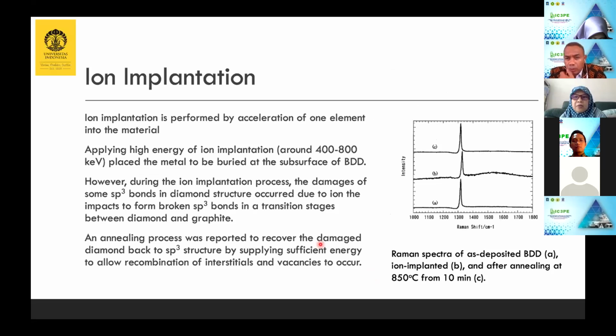The next is the ion implantation method. What is ion implantation? Actually, we use an accelerator to shoot one element into the materials. So with the accelerator with high energy, we can put the metals or particles in the subsurface of boron doped diamond. Because it will be deposited on the subsurface, the stability will be much better than electrodeposition.